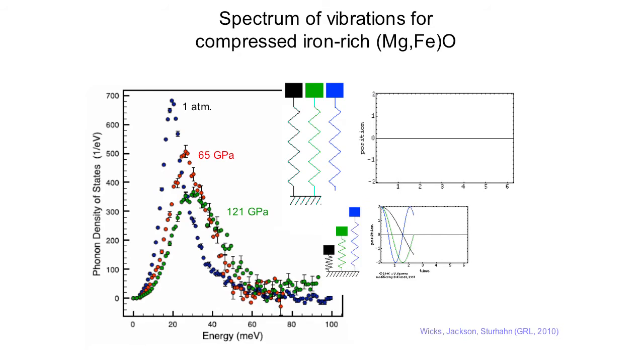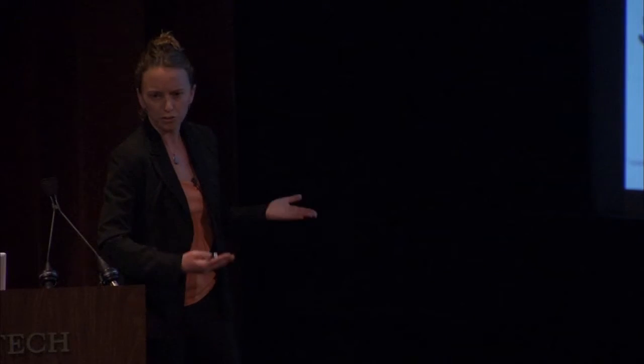And the rest of the modes are the higher frequency modes, which are depicted by the green and the blue springs that are moving at moderate to faster frequencies, which collectively, so if we extend and we look at the whole spectrum, they give us the total thermodynamic information, and that can give us the thermal pressure, for example, or the thermal conductivity.